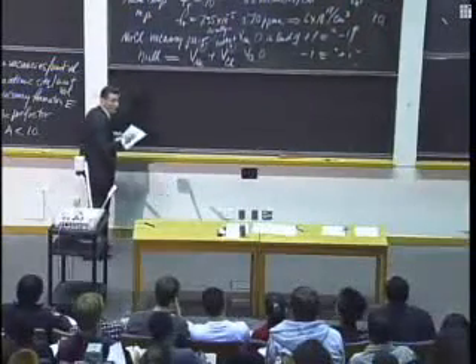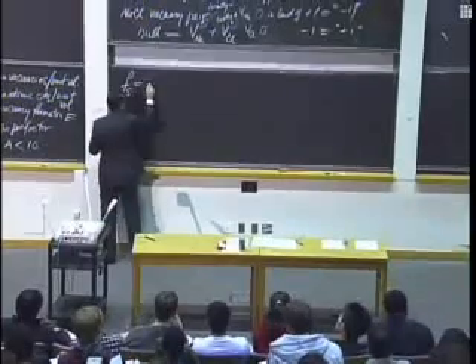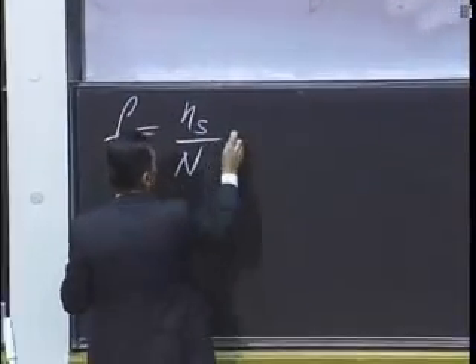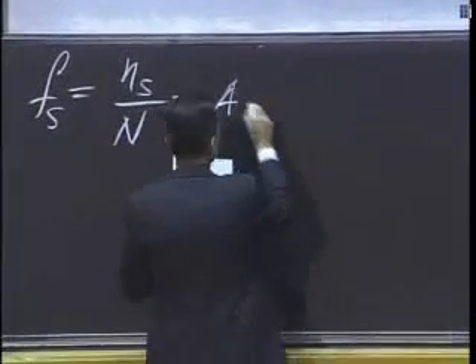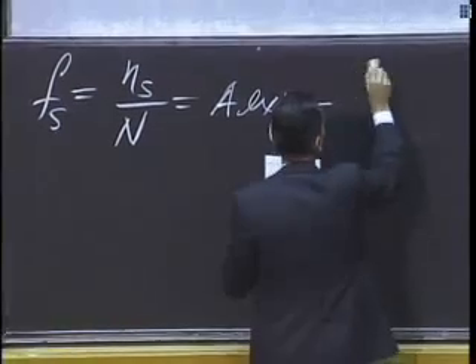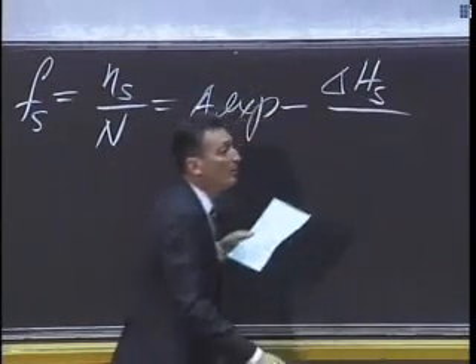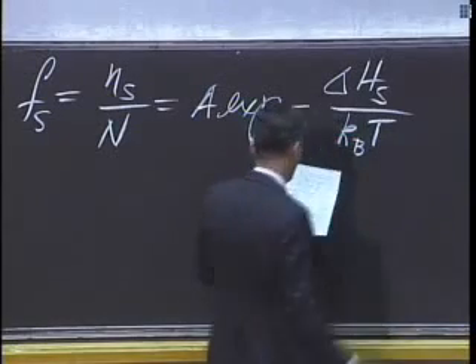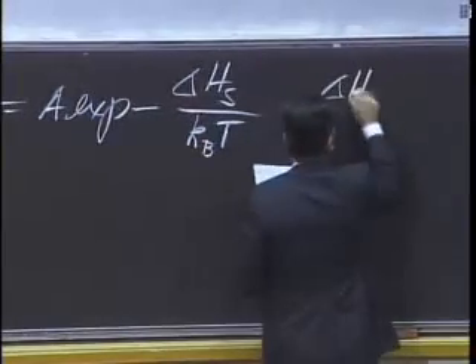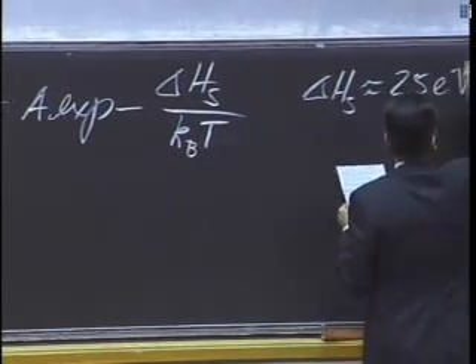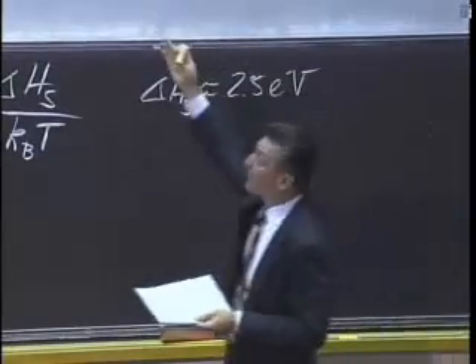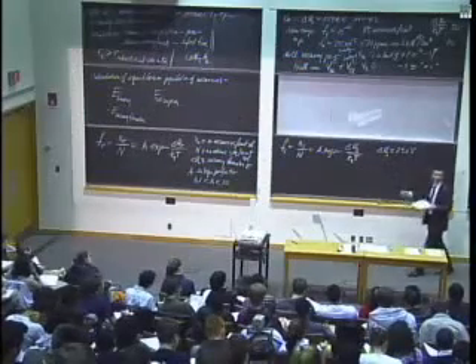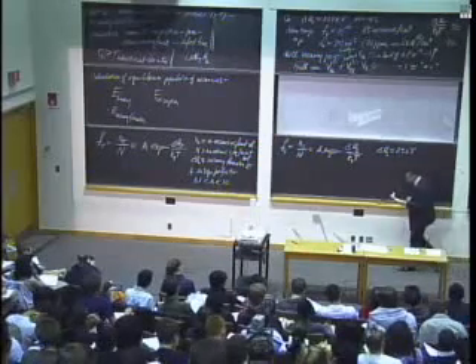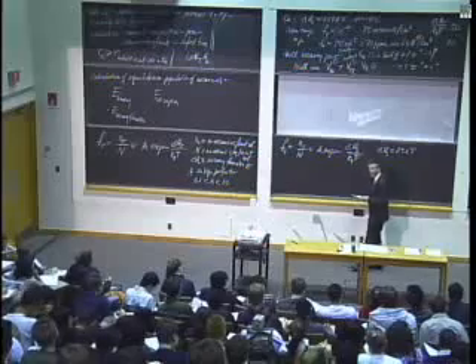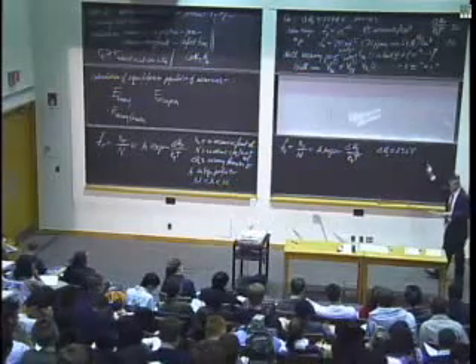Okay, and we can do the same as we did for the vacancy fraction and compute a Schottky fraction. What's the fraction of Schottky defects? It's going to be the number of Schottky defects divided by the total number of sites. And it'll be an equation of this form, some pre-exponential times the exponential of the ratio of the energy to form the Schottky defect divided by the product of the Boltzmann constant and temperature. And for sodium chloride, the Schottky energy is on the order of about 2.5 electron volts. And that's about double what it is for copper. And that makes sense. It should take more energy to make a vacancy pair than it does to make a vacancy. And Coulombic forces of attraction in ionic crystals are more intense than metallic bonding forces in metal crystals.